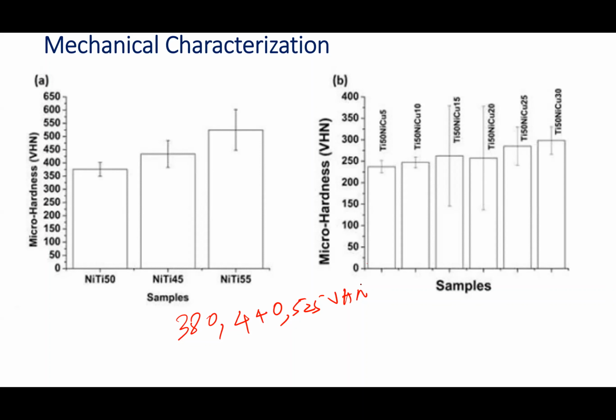Now, when we talk about the microhardness of the ternary alloy, the TiNiCu samples fabricated by this technique showed a microhardness in the range of 237 to 297 HV. The microhardness in these samples increases with increasing copper concentration, and a higher concentration of copper causes the formation of precipitates like TiNiCu2 and Ni2, which basically contributes to the increase in microhardness due to the internal stress. But in the ternary alloy with the inclusion of copper, the problem could be overcome, as the variation in hardness is more uniform across the sample. So this is almost a clear indication that a good alloy has been formed.